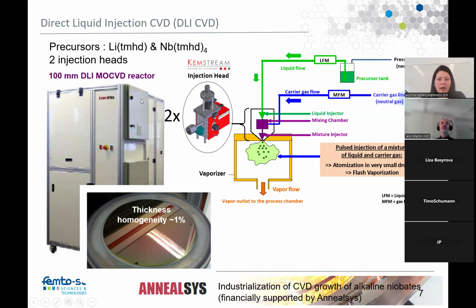Basically, we use these two injectors, so we can place one solution in one canister and the second in the other, and adjust very finely how much we inject of each solution. We can change easily from one deposition to the next just by changing the injection rates, and the injectors are controlled by computer.